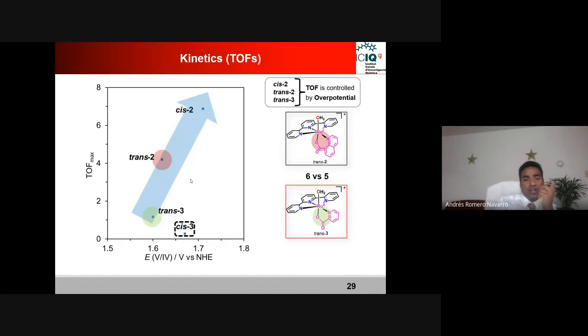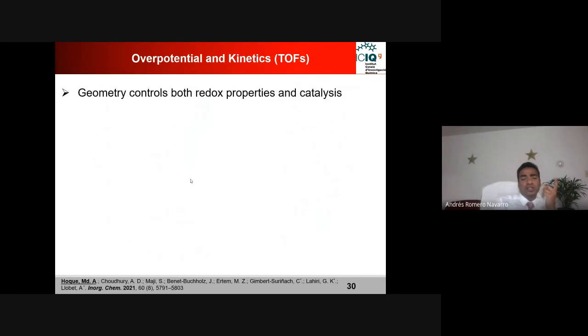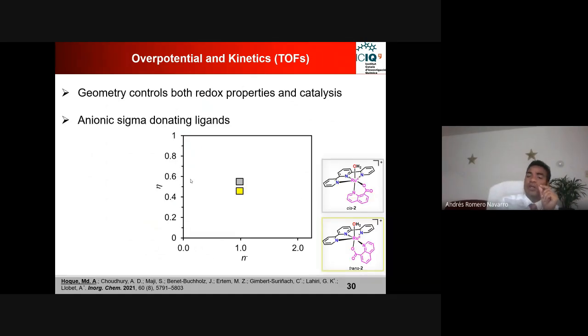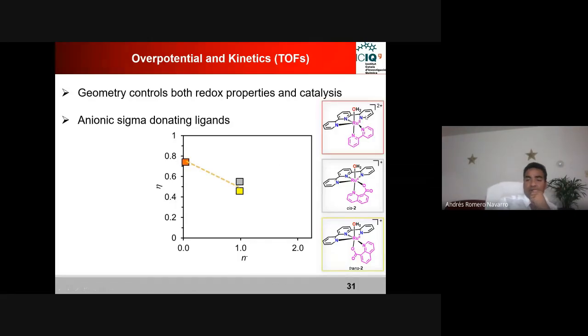So now we got that system, and basically what I'm showing here is that geometry can control both the redox property and catalysis. But in terms of overpotential, in this molecule we have one sigma donating ligand, this carboxylate, and it has an overpotential approximately between 0.5 to 0.6 volts. This is the absolute overpotential I'm saying. And this compound has already been reported where you have this neutral bipyridine ligand, and it has an overpotential of approximately 0.754.